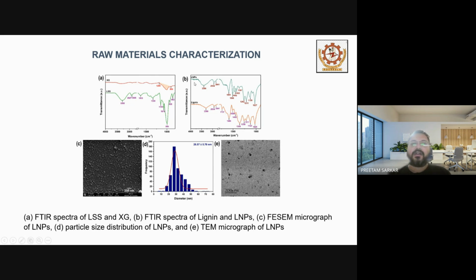We do this as well for the lignin, the nanoparticles and the lignin itself, because the lignin nanoparticles were prepared from the lignin which we bought chemically from Sigma. So we did this FTIR characterization. We also did the FESEM characterization of the lignin nanoparticles. We did particle size distribution, and we also did TEM, transmission electron microscopy, of the lignin nanoparticles, because we wanted to understand the morphology of the lignin nanoparticles and how they're distributed.